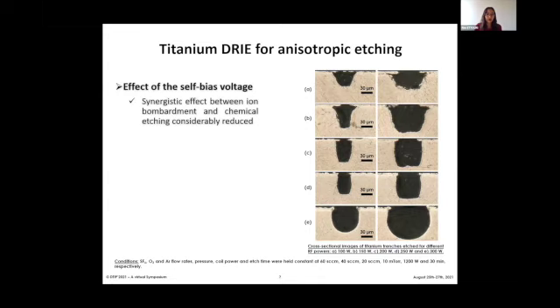Contrary to what is often observed in RIE systems, in our ICP system, DC bias increases with decrease in pressure at constant RF power. So at low RF bias powers, underpassivation is observed. So there is lateral etching, which reduces the vertical etching. As the bias increases, the etching process relies mainly on ionic sputtering of the non-volatile products. So the synergetic effect between ion bombardment and chemical etching is considerably reduced, resulting in a stabilization of the etch rate and profiles that tend towards anisotropy, with the most suitable one in D.